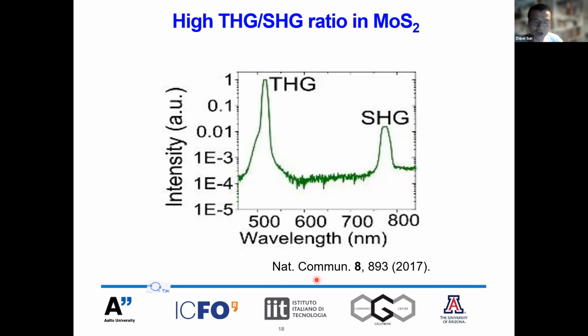If you go to a nonlinear optics textbook, you will find that the conversion efficiency of a nonlinear process normally decreases with the order. That means the third harmonic generation is always weaker than the second harmonic generation. But from the results we get here, you can see completely different results. What we get is a third harmonic generation efficiency around 30 times larger than the second harmonic generation. This is a very big surprise for us.